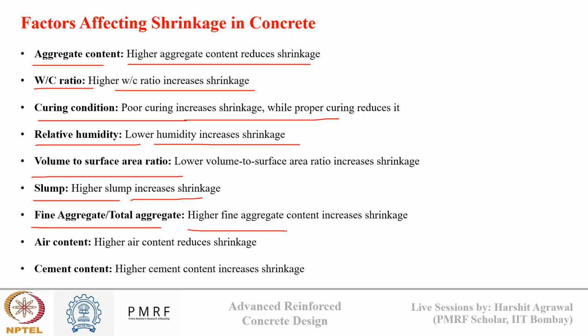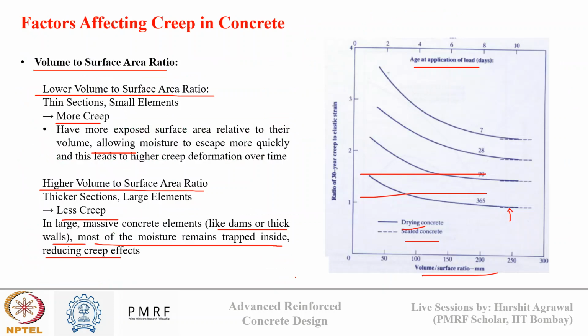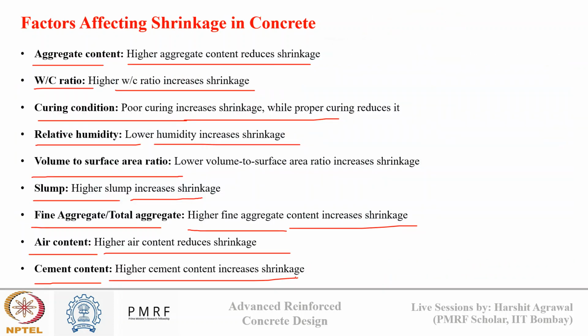Fine aggregate: the higher the fine aggregate proportion, the more paste content in the concrete, so there can be more shrinkage. If there is more air content, it will reduce the shrinkage, because it provides relief inside the concrete. And the higher the cement content, the more heat of hydration and the more cement paste, so more shrinkage. So every factor is related to the movement of moisture: the more paste or the more moisture inside concrete, the more shrinkage issues. Okay, I have not discussed this in detail because it is already similar to what we discussed in creep, so that's why I moved quickly.